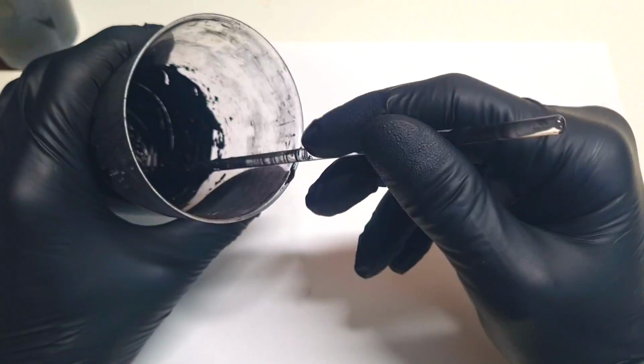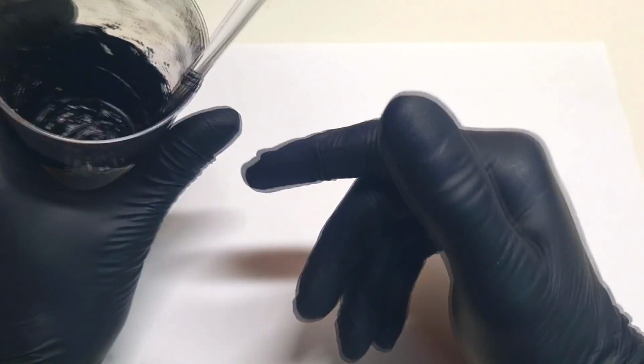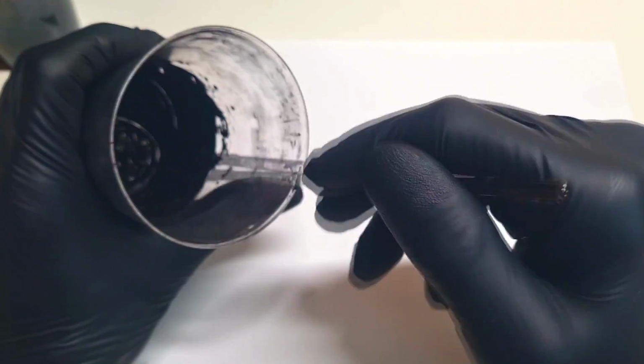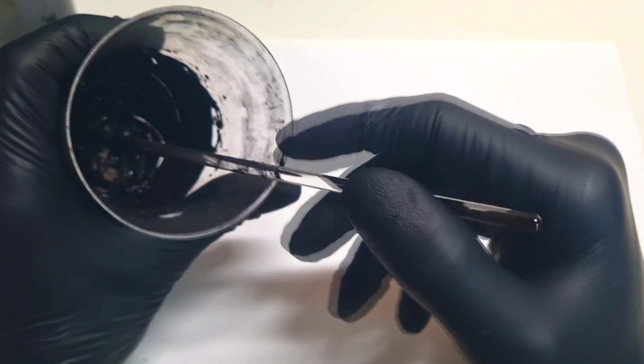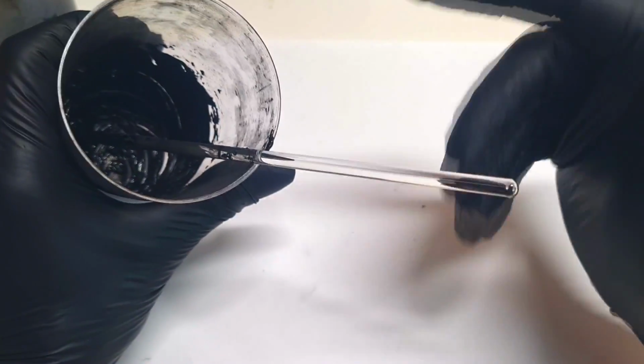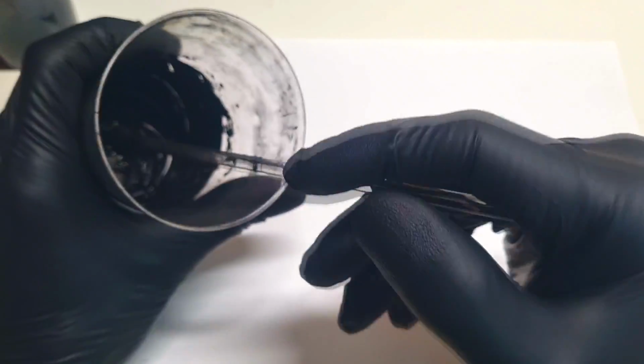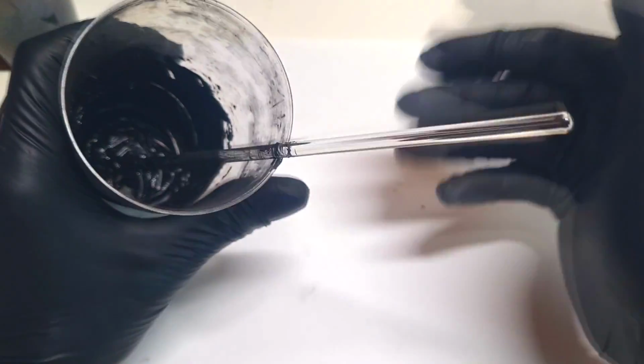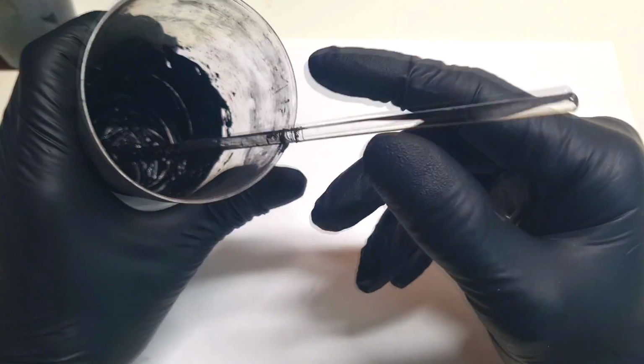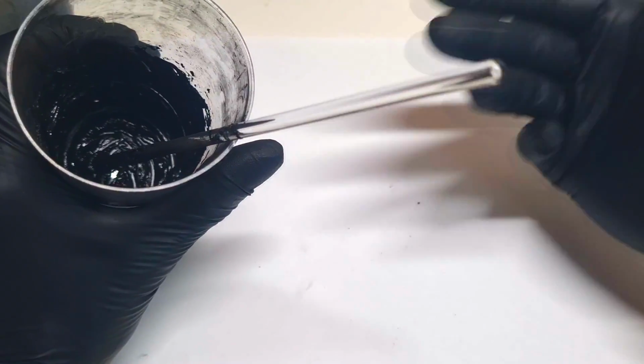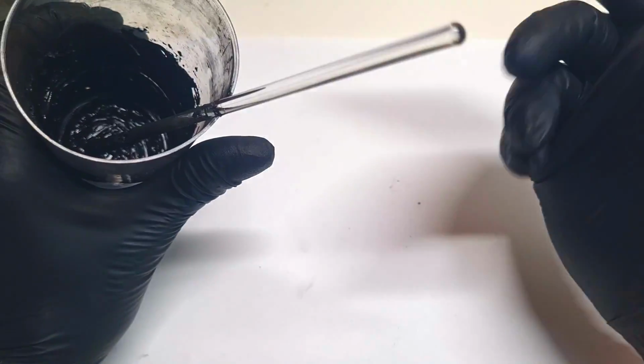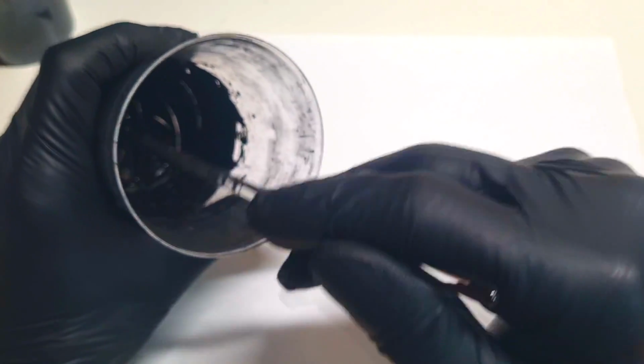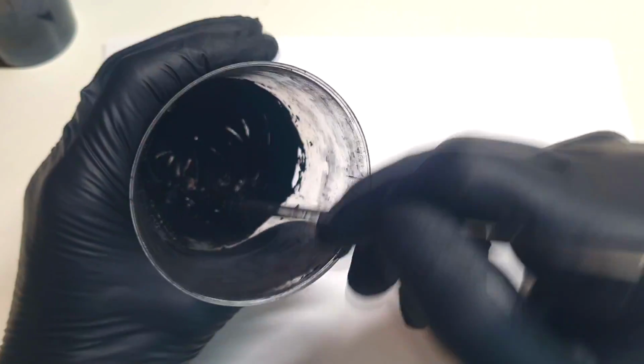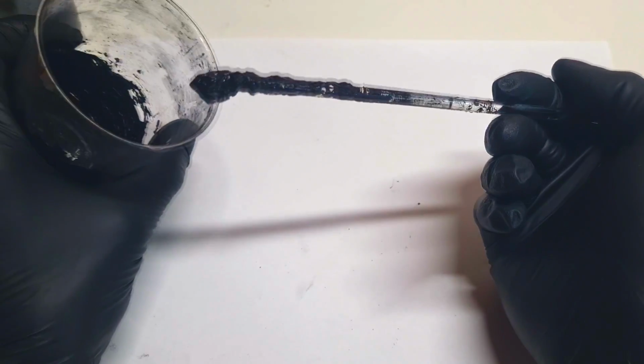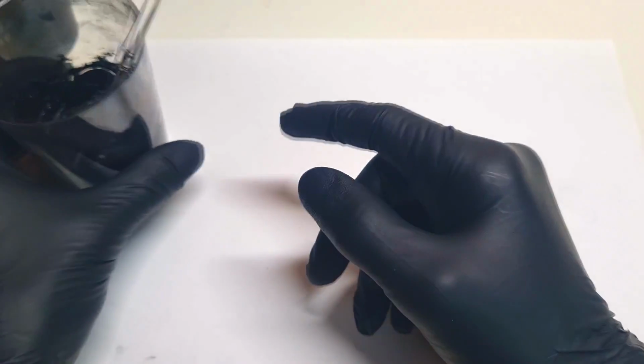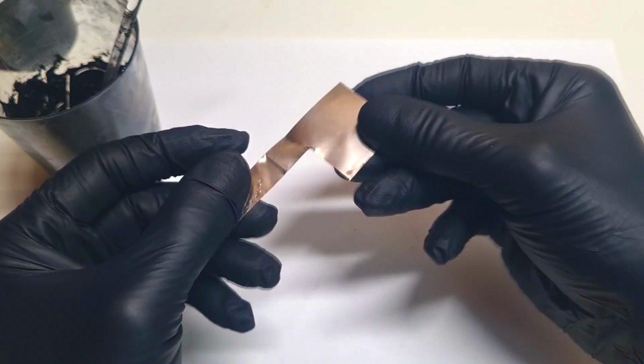The mixing ratio will be 8:1:1, which means that you will use 8 grams of active material, 1 gram of binder and 1 gram of solvent. But actually you can also add a little bit more water if you want, because in the end when you dry the electrode, all the water will evaporate. And when you have your mix, like I have over here, this slurry you need to coat on some current collector.